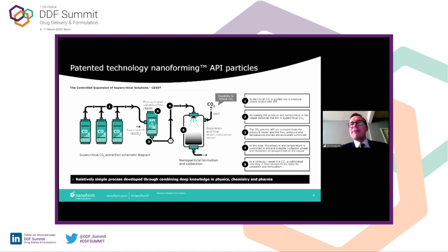For Helsinki and Finland, they're quite used to managing snow, but it is quite fascinating to watch. We form this mountain of snow in the collection chamber. Once we've collected enough material, we depressurize the system and allow the CO2 to sublime off as a gas, leaving a dry nanoparticle powder. It is possible to make this process continuous, and we are looking at that right now.